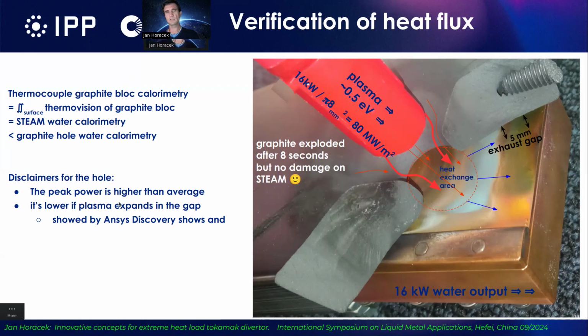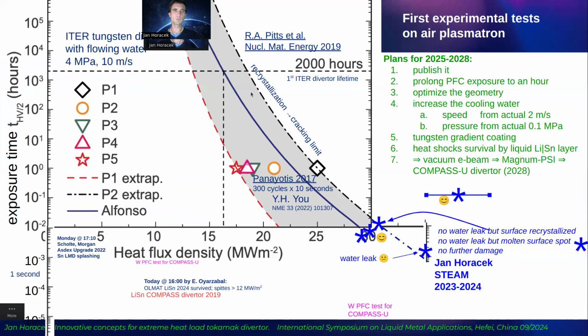But unfortunately, then we did simulations using ANSYS Discovery that, in fact, it doesn't do this. So the plasma goes here. It does not give its energy in this circle. It does it away, through the exhaust gap with 5 millimeters. So in fact, we cannot believe this value. But what we believe is the measurement using the graphite, and this is shown in this graph, where